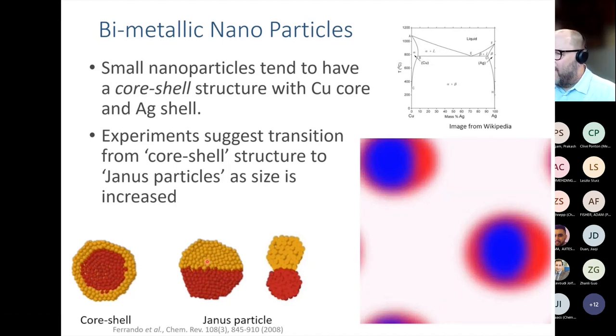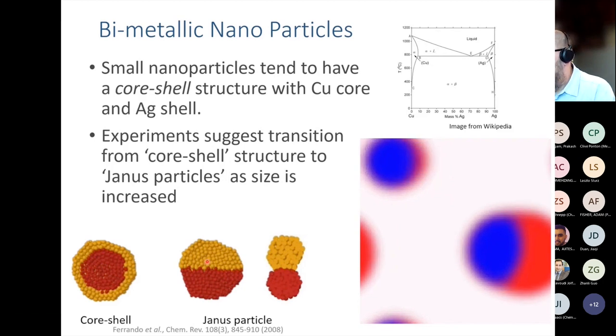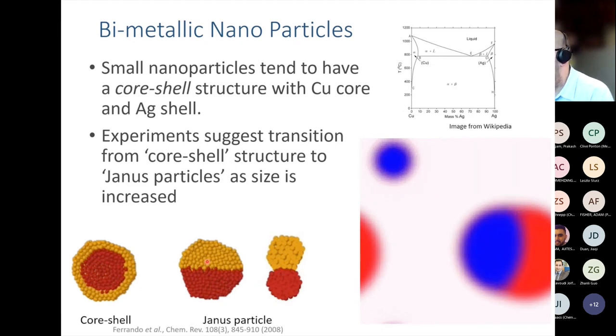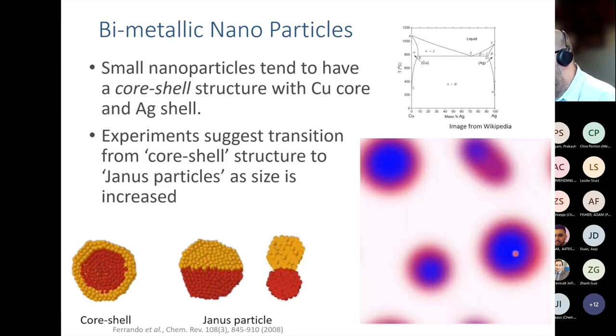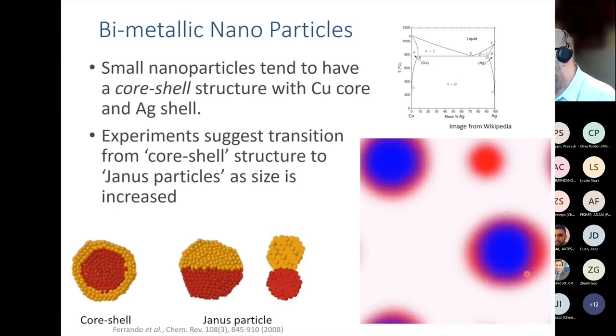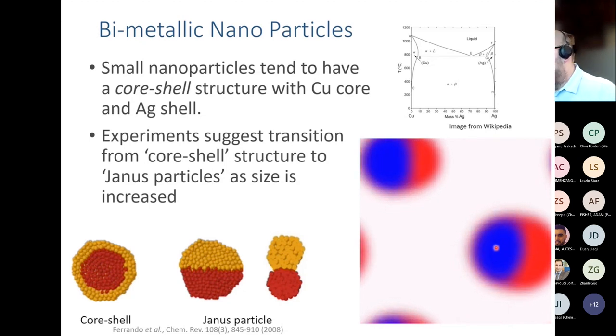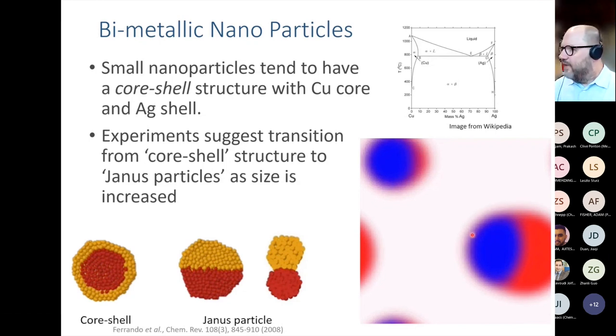And we try to understand whether this is really a size effect and whether we could develop a model that would allow us to move into bulk phases as well. So this is using the father of most phase field theory, the Cahn-Hilliard theory, and we simulated the separation and evolution of the particles. And what we clearly see when the particles are small, they form a core shell structure with a red layer on top of a blue core. As they get bigger, the core moves towards the side, and the largest particles in the end clearly have a Janus type configuration, but they're also not spherical. They change the shape slightly.